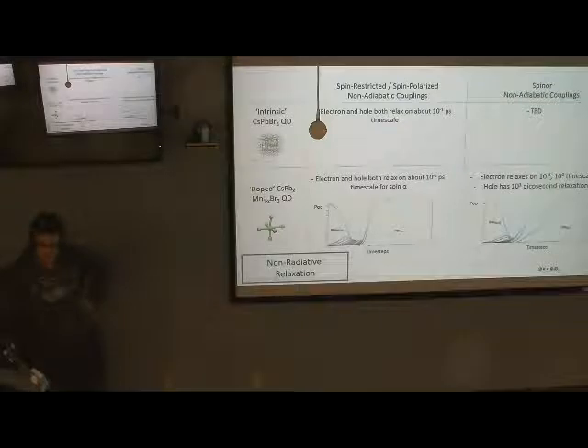You see that happens pretty fast in the conduction band. And then even once it hits the dopant states, which are close to the band edge, it takes a little bit of time. But after about 300 time steps, all of them relax to the band edge.